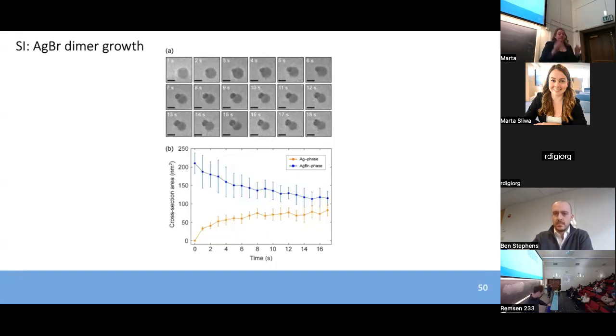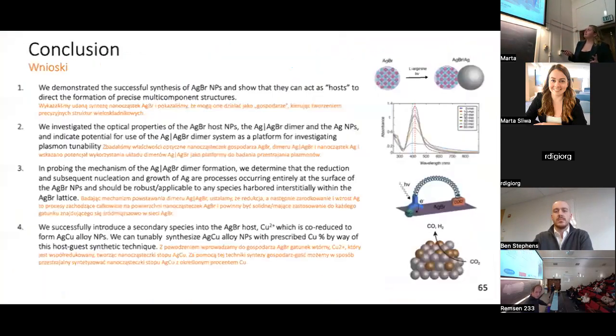When we dimerize and form that silver bromide dimer, I just didn't include the ligands for clarity here. So there's oleate and ascorbic acid on the surface. When we dimerize, we suspect, or are pretty confident, that that oleate on the silver bromide does not migrate to the silver phase of the dimer. They're staying on that silver bromide. So this is ligand free.